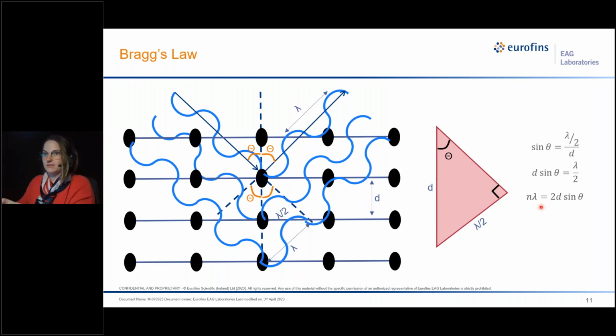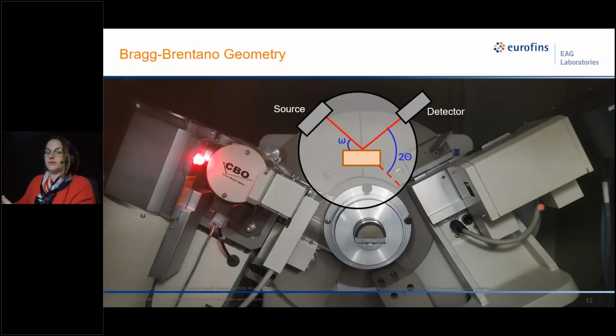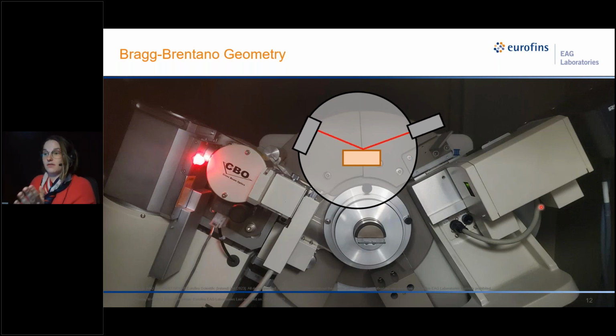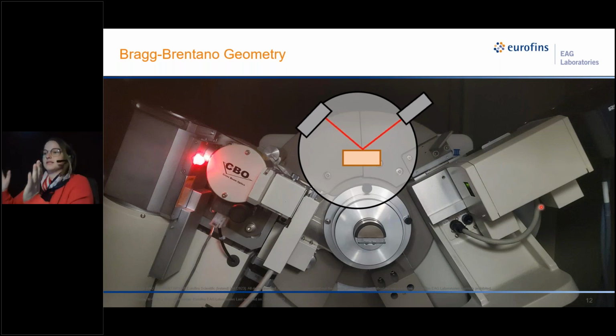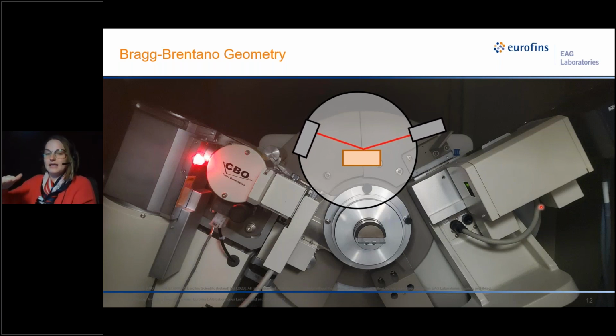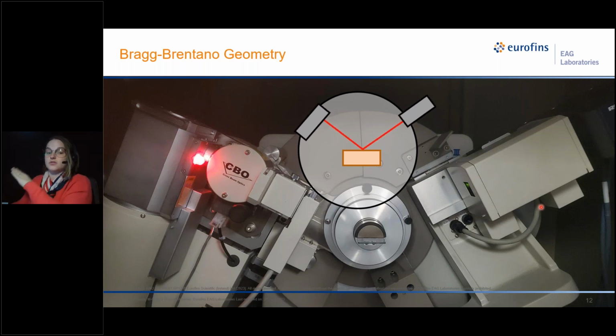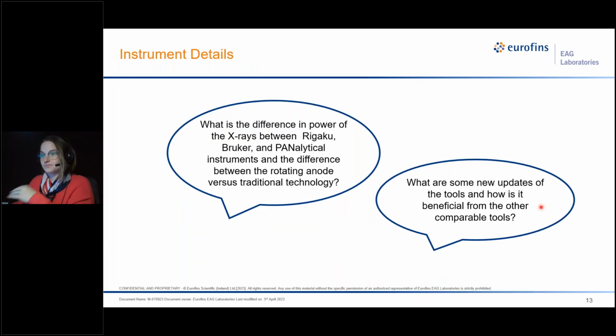A lot of diffractometers you're going to see have a typical geometry called Bragg-Brentano geometry. And what that means is that the source on the left side and the detector on the right side are going to move symmetrically to each other on what we call this Bragg circle. And what that is going to do is it's going to analyze any planes that are parallel to the surface of the material, because again, we need those lattice planes parallel to create those constructive interfering waves of X-rays.